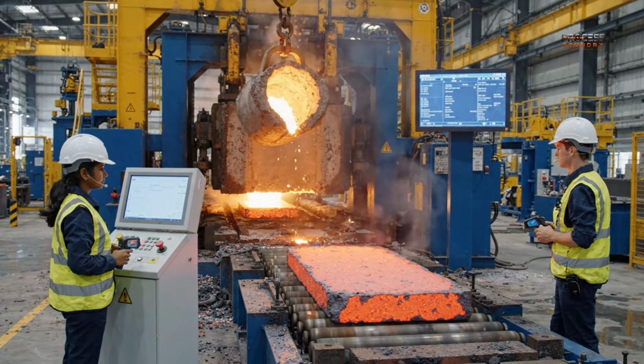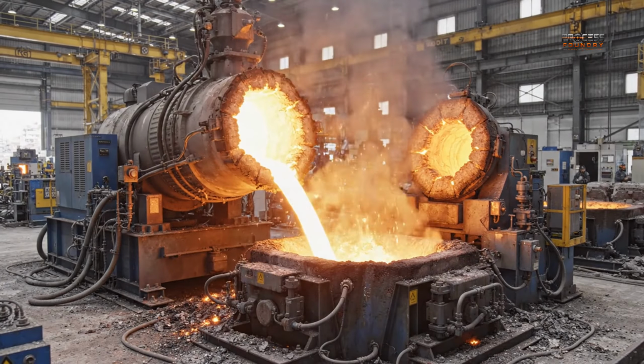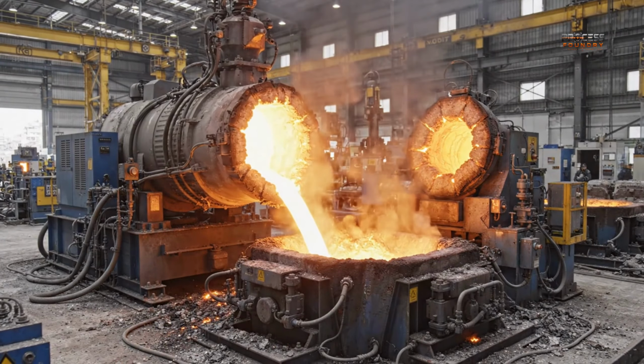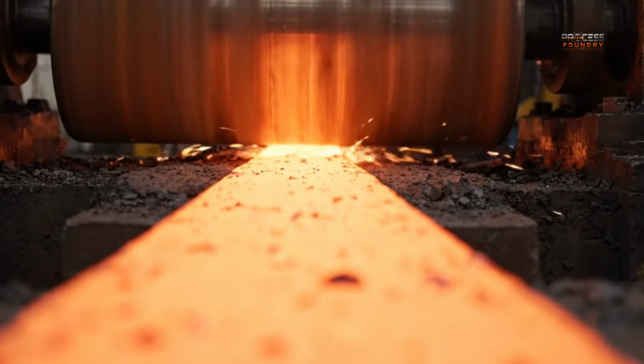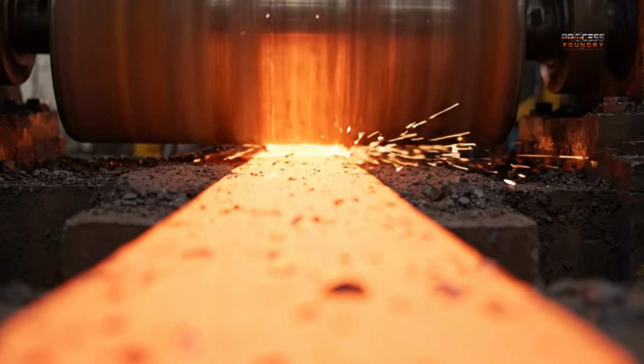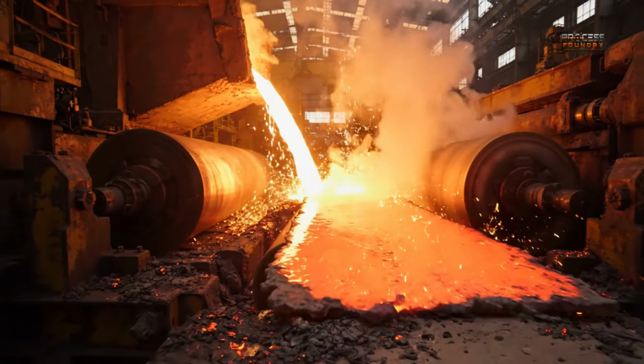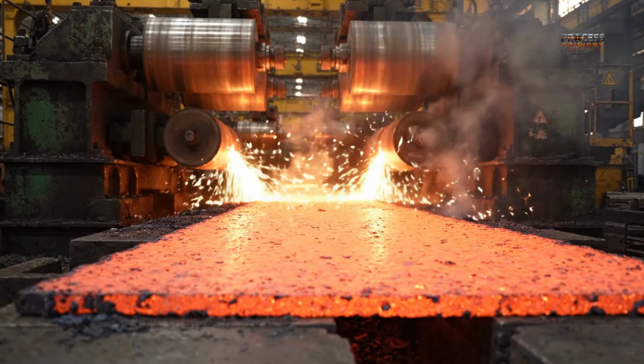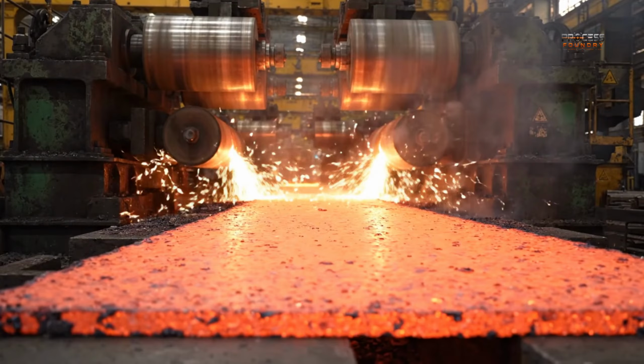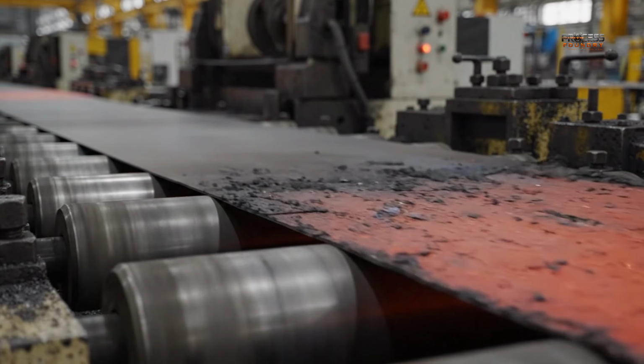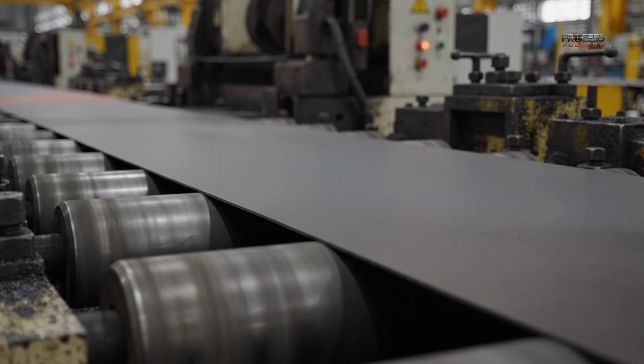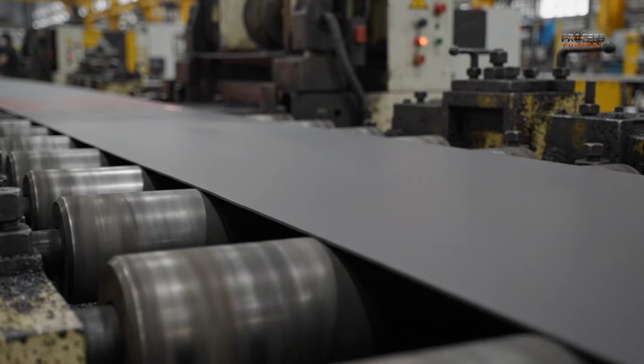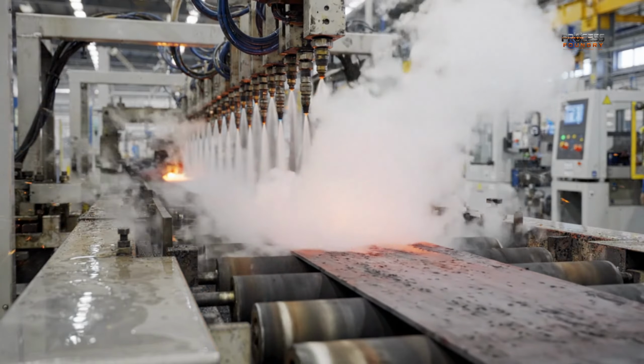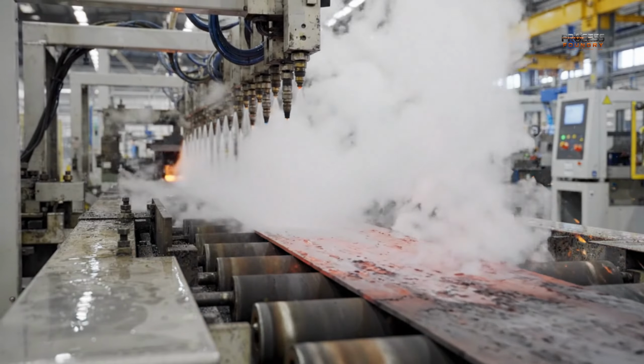The induction furnace tilts, pouring a beautiful stream of liquid steel into the casting system. This is when advanced thin strip casting technology comes into play. No need for giant block billets. The liquid steel passes through 2 cooling rollers and immediately solidifies into a glowing red thin steel strip. The cooling mist system gently lowers the metal's temperature, bringing the steel to a static state.